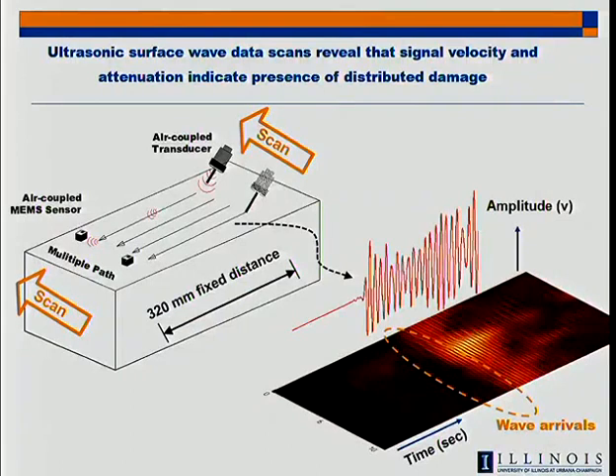So for each one of these lines, let's say we get a signal like this, right? But if we get a lot of signals, a lot of data, and this is what we're talking about, collecting tons of data, what do you do with it? Well, one way is to create an image. So if we now convert the single line to a new scale, let's say instead of having positive and negative values, we give the positive values a bright color and the negative values a dark color. So now we just transform that to a line of color. And then we stack parallel lines together. Then we get immediately an image. And in the ultrasonics community, they call this kind of stacked time scans, where it's converted to color or grayscale or something, B scans. It's an outdated term. It means brightness scan. So it's usually conveyed in terms of brightness. But immediately, we see a lot more information that as users, as an engineer, can interpret what's going on.